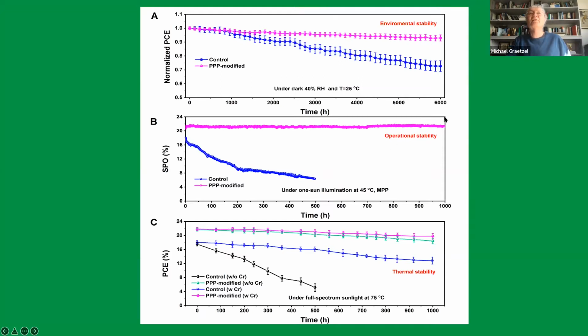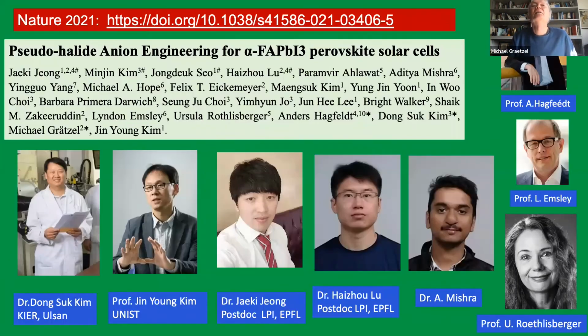But the operational stability is key. I mean, there you hold the cell under full light and you draw maximum power and you increase the temperature at 45 degrees, here even 75 degrees. So that's an amazing result. And yeah, the efficiency decreases only very little. So recently we published 2 papers, one in Nature and one in Science.